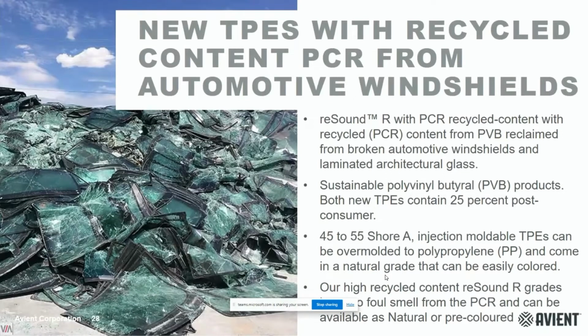And up to now, the only way of these windshields, and you have to bear in mind that each year around 75 million windshields are wasted. The only way was to scrap it on the scrap yard and to leave it there without any added value to this material. This mix of glass and PVB make it up to now not suitable to recycle it. But we have succeeded to get the right collaboration with a company that delivers us the PVB content from these windshields, and that way we give an added value to this waste, and we reduce this waste.